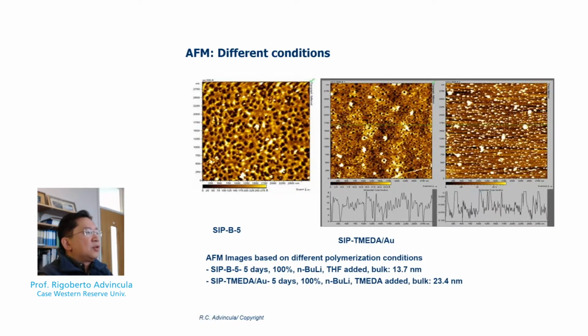So some of this early work resulted in the following. We were able to control the grafting of these polymers on silicon wafer and gold surfaces as well. This was done by using n-butyllithium on the diphenylethylene initiator. And for example, the left AFM picture shows the grafting on a silicon wafer surface, and the right one on a gold-coated wafer, which actually showed a thicker brush of about 23 nanometers versus 13.7.